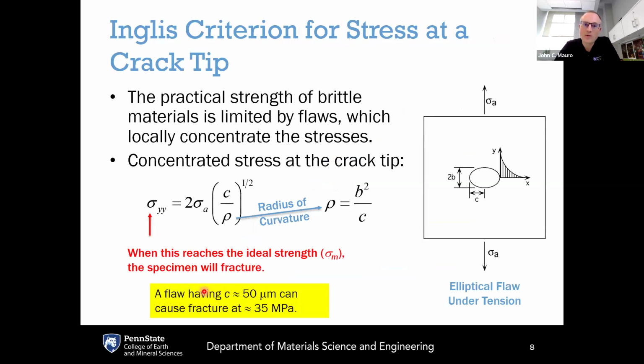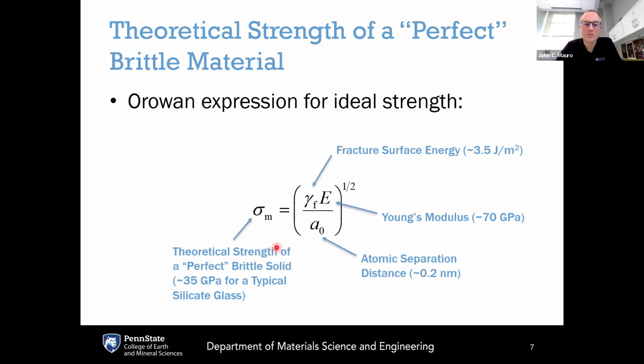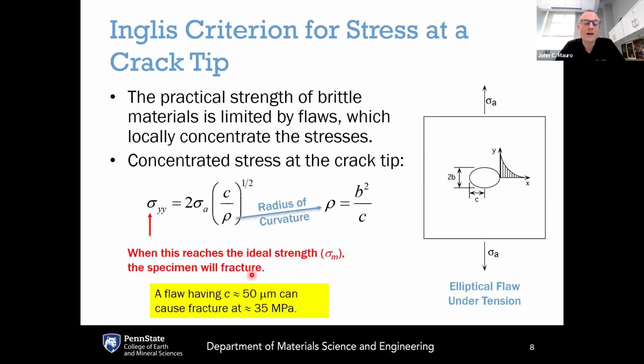The original theory for the incorporation of flaws into the strength of a brittle material was done by Inglis. Inglis considered, what if we have an elliptical shaped flaw that is in the interior of the brittle material? So for example, this would be an elliptical flaw that has the dimensions shown here, placed in uniaxial tension with an applied force. Inglis calculated how much of a compromise of the strength you would get. For example, if you take this perfect brittle solid with an ideal strength on the order of 35 gigapascals and introduce a flaw on the order of 50 microns, then this can actually lead to fracture at a dramatically reduced strength of about 35 megapascals.